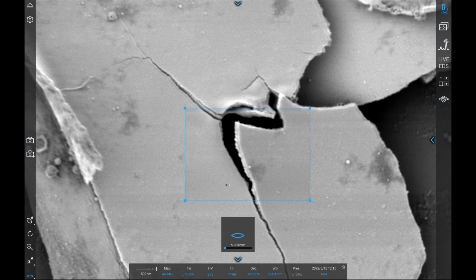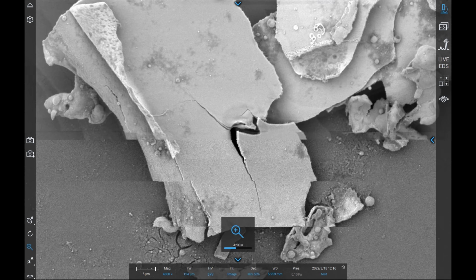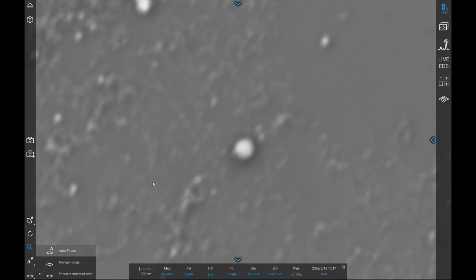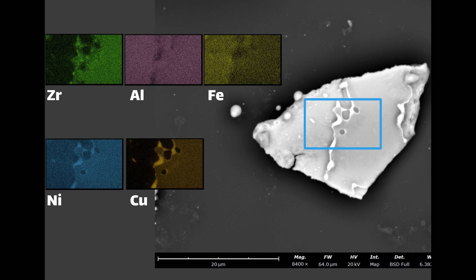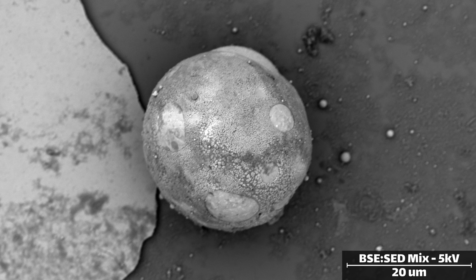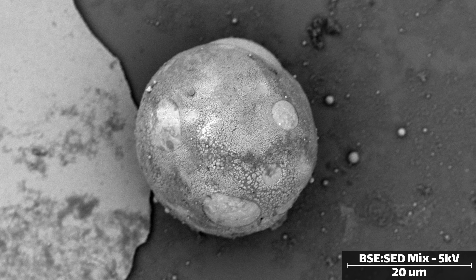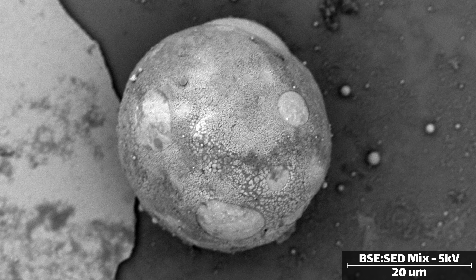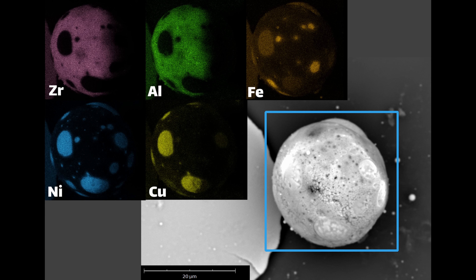The most prevalent feature by far are these large fragments of the thin film that just flaked off en masse. The layers I sputtered are 100 nanometers thick, so these flakes are usually 400 to 500 nanometers thick depending on how many layers stuck together. If we look at large particles — say 10 to 30 microns — you'll often see a round spherical blob that has a mix of a few elements and then smaller hemispheres dotting the surface. The hemispheres tend to be made of nickel and copper alloyed together.